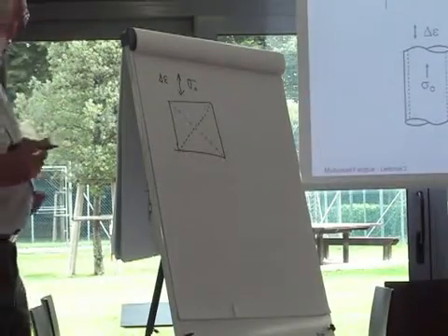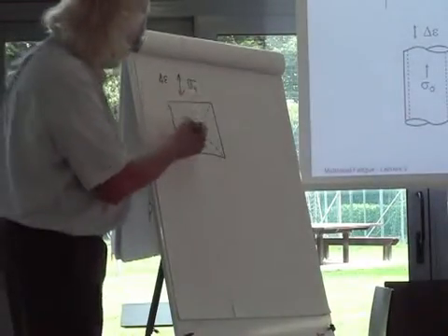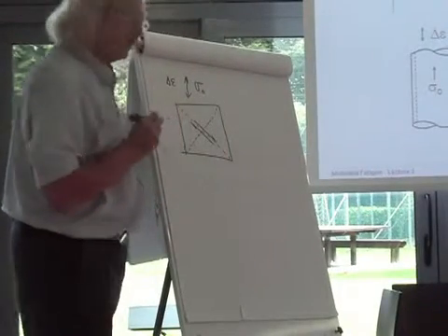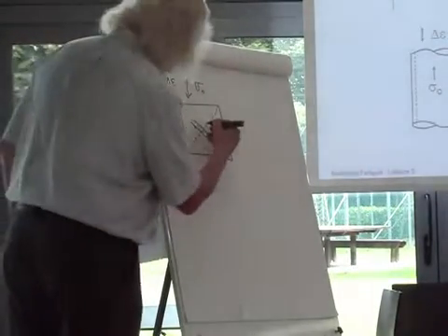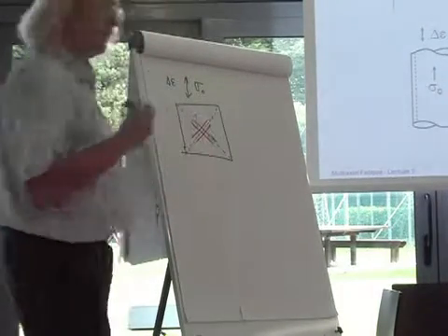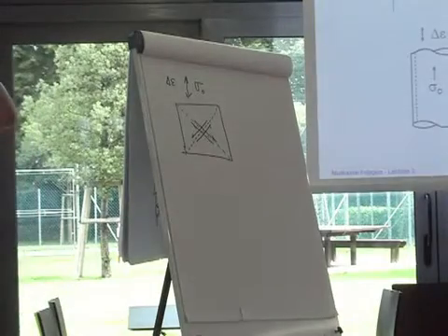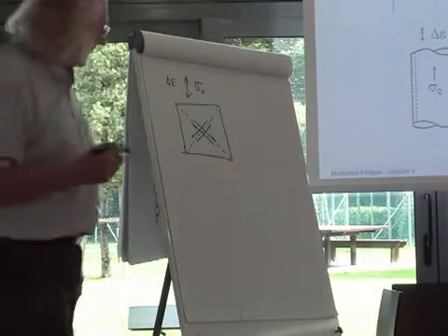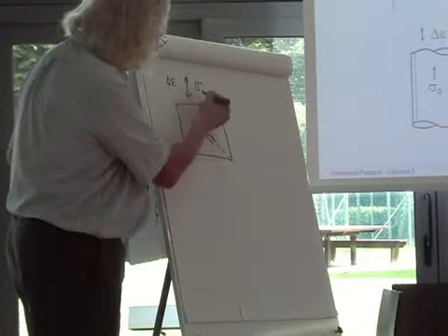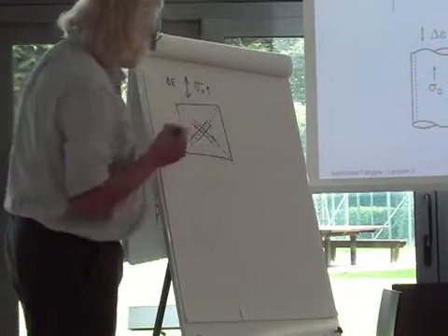And if I look at this strain delta epsilon, then this will produce a shear strain that exists on this plane like this. Right? And it will also produce a shear strain on this plane that looks like this. Right? Both of those two 90-degree planes. And then there will be a mean stress, and so this mean stress exists in this direction, right?